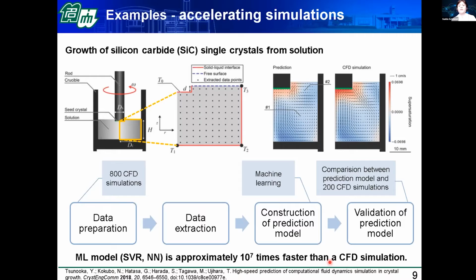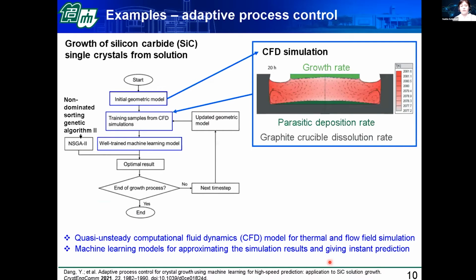And this was the basis for the authors to use this method for coming up with an adaptive process control. At first, this uses the previously shown approach in principle for determining the growth rate of silicon carbide, the parasitic deposition rate, and the crucible dissolution rate in a CFD simulation, which is then used for training a machine learning model.